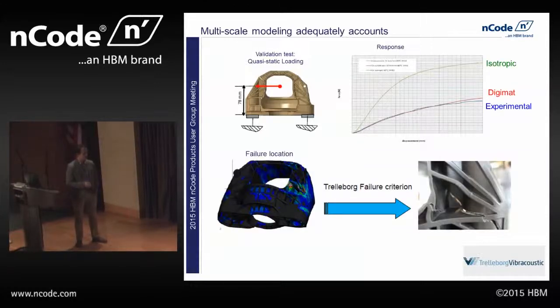And so what they did is they took their part, they loaded it transversely, and then they compared a couple of different analysis approaches with their experimental data. So what you see over here is a force versus displacement graph. You've got the isotropic curve in green up here. So this is kind of taking the numbers directly from a data sheet for this material and plugging into your model. And then in blue, you've got your experimental data, and in red, you've got the Digimat. And you can see that using Digimat with your finite element analysis gave them a pretty much perfect description of the stiffness of the part.